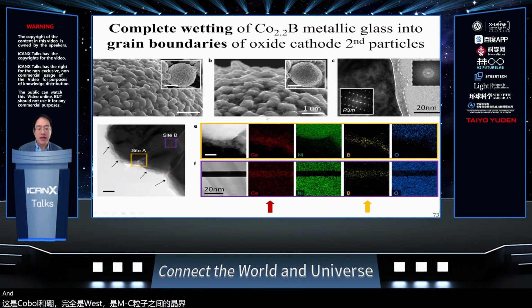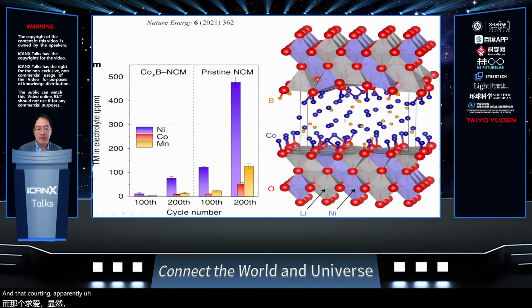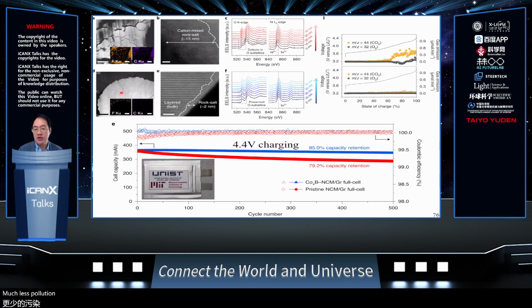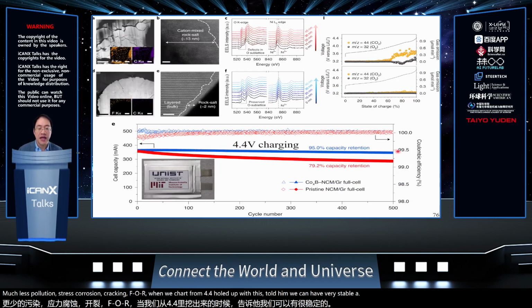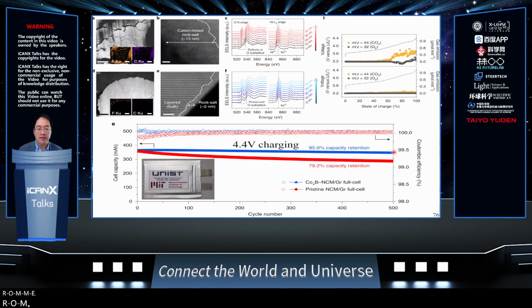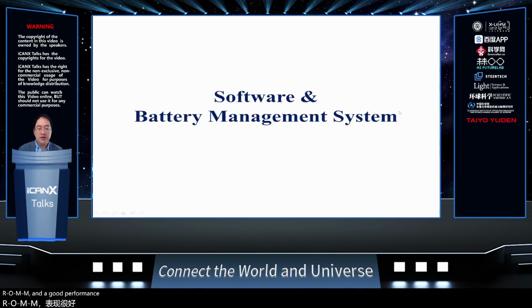And that coating apparently reduces the amount of transition metal dissolution. So this is with uncoated material, this is with coated material. We see much less transition metal dissolution, much less corrosion, much less stress corrosion cracking. And so when we charge to 4.4 volts with this coating, we can have very stable capacity retention and good performance. So in the last 5 minutes, I want to also talk about more system level issues.